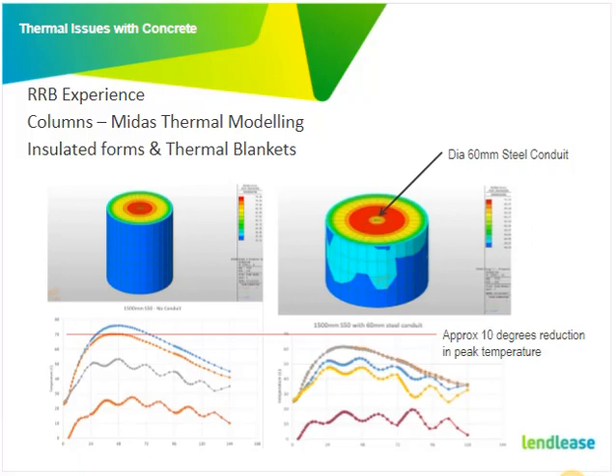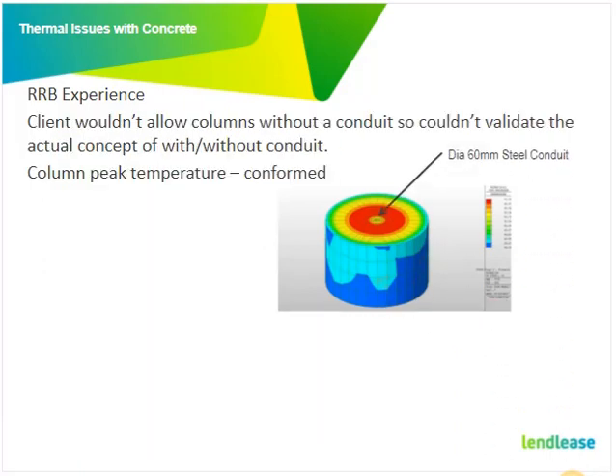So it just kind of changed, and on site after we'd done the pour, you could actually feel the heat coming out of the centre of the tube as the concrete was curing. We got about a 10-degree reduction in peak temperature from doing that. And we managed to achieve compliance for all our columns, which was a good outcome.